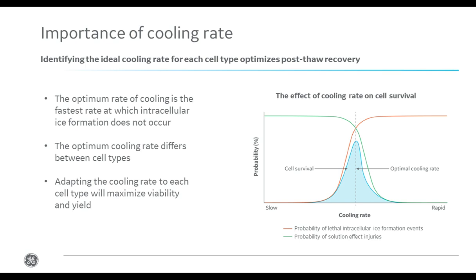So to carry on with the importance of cooling rate, when optimizing a cooling rate for your cells, an idealized graph will look something like the one shown on this slide. At very slow and rapid rates, the post-thaw recovery is reduced. In mammalian somatic cell suspensions, optimal rates are around 1 degree a minute, while 10 degrees a minute is usually too fast. Cooling as low as 0.1 degree a minute is often acceptable, however, although it does take a long time, but is particularly advantageous for organoid and tissue preservation, especially tissue-engineered constructs used in regenerative medicine.